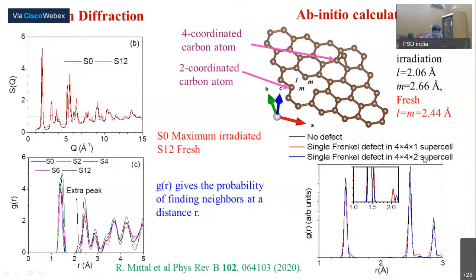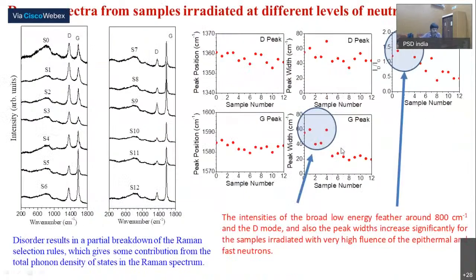And these are the Raman spectra for all these 12 graphite samples, and we see that there are two peaks, a defect peak and a graphite peak. As we increase the level of irradiation, the intensity of this defect peak is increasing. This is the maximum irradiated sample, and this is the fresh sample. So we can see that with increased fluence the peak positions are more or less the same, but the intensity of the defect peak and graphite peak is increasing, and there is also an increase in the width of the graphitic peak. This increase in intensity of the defect peak is due to the breakdown of the Raman selection rule, which gives a contribution from the total density of states in the Raman spectrum.